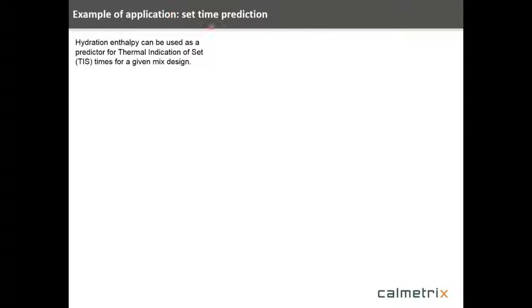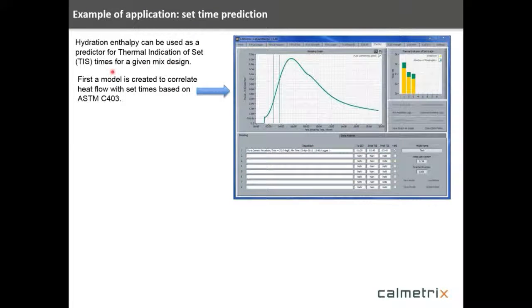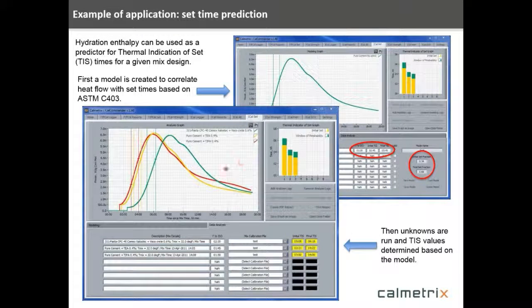We can do something similar with set time prediction. We can use the power curves now and model that using your classical ASTM technique for measuring your initial and your final set times. And so the way we do that is, again, we first create a model. So we run the heat flow curves. We then input the data from your ASTM technique and create a model based on that. And then we can come back and run unknown samples, fit them to that model, and from that model, it develops the initial and the final set time numbers for you.